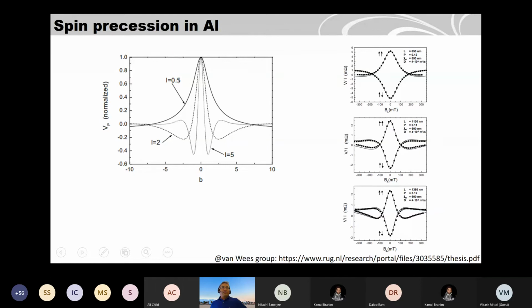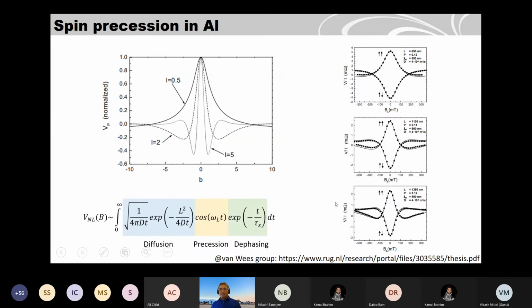Okay, so what you will see is that with different lengths of the channel, 0.5 to 2 micrometer, 5 micrometer, you should see the Hanle line, the voltage signal with magnetic field, that will have different line widths. When you have such a signal for the longer channels, that means spins are precessing completely, and so all the spins are out of phase here. So people have done such measurements to find out spin lifetime in the different channels. And this is a simplified equation you can use to find out how the spin signal voltage depends on the diffusion constant, because spins have to diffuse in the material. This is the precession term, this is the Larmor frequency term, and dephasing is the spin lifetime.